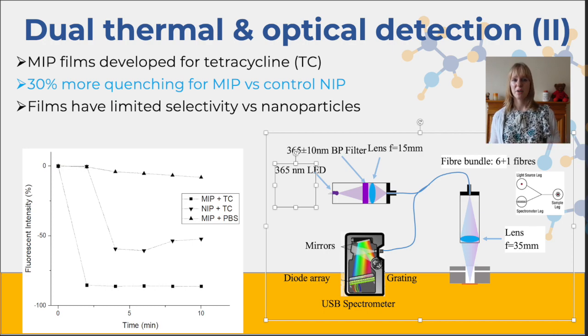And you can imagine if we want to measure over prolonged periods of time, so let's say over, for instance, 2 weeks, this can really lead to problems. Because it might be that your whole sensor surface is fouled with other compounds before you can even measure. So that's why we think the way forward is to still look at either nanoparticle systems or by playing around much more with the monomer composition in the films.